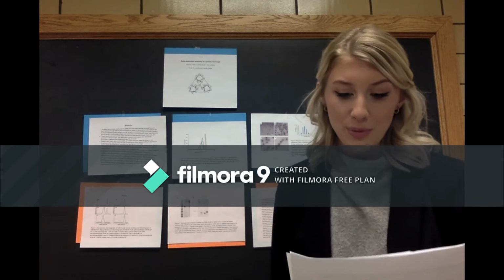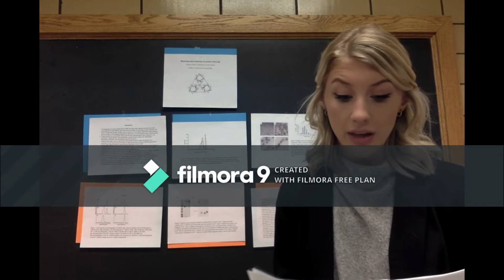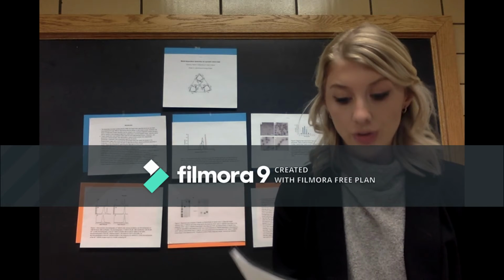To equilibrate TET8M with metal ions, the de novo designed metal binding coiled coil was reported to have low micromolar affinities for several divalent metal ions, such as nickel, copper, cobalt, and zinc. They evaluated the potential of the TET8M construct to assemble into protein cages in the presence of these ions. Nickel appeared to be most effective at causing oligomerization, as concentrations between 20 and 200 micromolar resulted in the largest fraction of TET8M being converted into high molecular weight species.